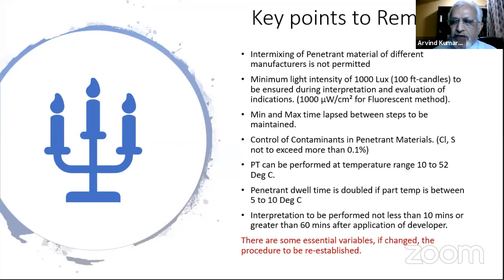For example, I do the cleaning of a surface before I apply a penetrant. Now, how much time should I give after cleaning before application of the penetrant? I cannot give unlimited time. I clean the surface now and I apply the penetrant after 2 hours. Maybe my environment is such that in 2 hours, I'm again spoiling my surface and it may not be good for doing a penetrant test. So these things have to be established as a procedure that, yes, if I allow half an hour after cleaning, the surface doesn't get deteriorated, I'm able to still pick up the indication.